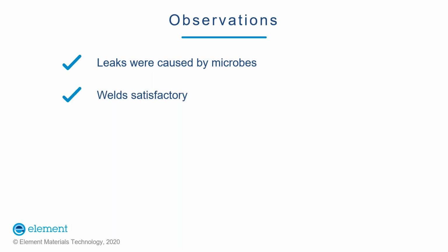Mechanical and chemical properties of the weld and the base metal were thoroughly checked. Metallurgical assessment of the weld and base metal did not reveal any manufacturing or welding defects. Hence, welding was found to be satisfactory. The failure was caused by stagnant water that remained in the pipes after the hydrotesting. The rapid corrosion, just 2 months, is another strong indication of MIC.